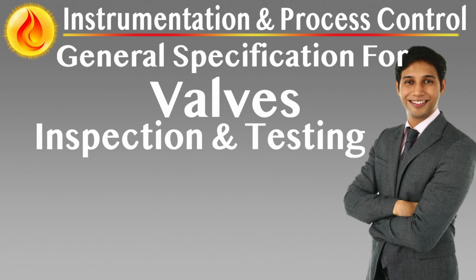Non-destructive examination, NDE, shall be performed in accordance with governing standards such as ASME Section V or ASTM specifications. Radiographic testing, RT, ultrasonic testing, UT, magnetic particle inspection, MPI, and dye penetrant testing, DPT, must be applied to valve components as defined in the applicable MES specifications or material requisition. NDE results must be traceable to heat numbers and casting or forging identifiers. Final NDE records shall be included in the valve dossier submitted with each batch.